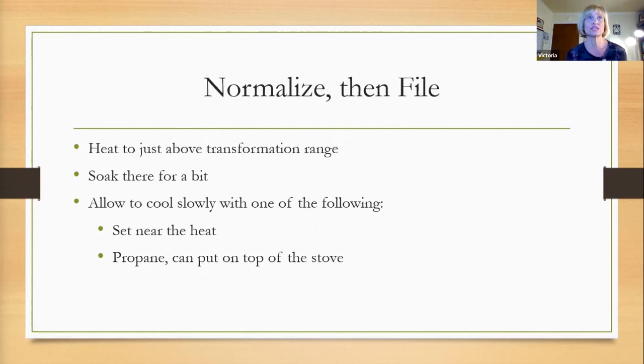So these are the steps: transformation range, soak there for a bit, and then allow it to cool slowly. And by cooling slowly, I don't mean chuck it on the floor. That is actually a quench. It's an air quench. I mean cool slowly with some heat still applied. And that is set it near the fire in your forge. For propane, you can put it on top of your forge.